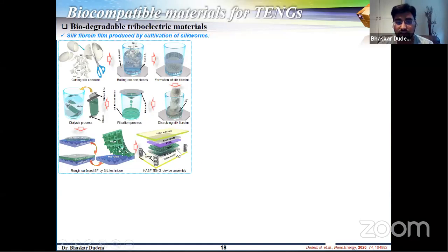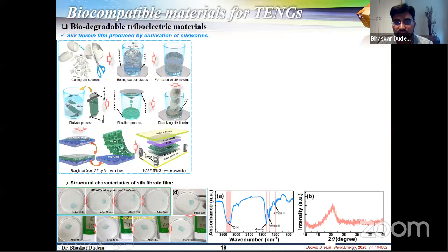So we have used the silk film as a positive material, and we have used that to convert into electricity. At the same time, the novelty of this work is that we have treated this silk film with alkali treatment. We used some alkali treatment to make it robust, so that it can be sustained in humid environments too.